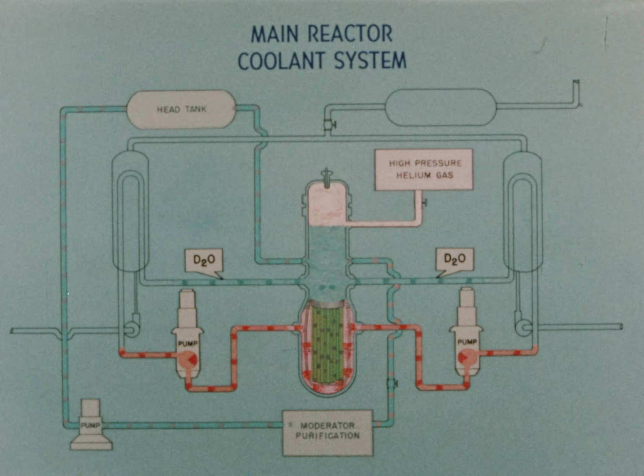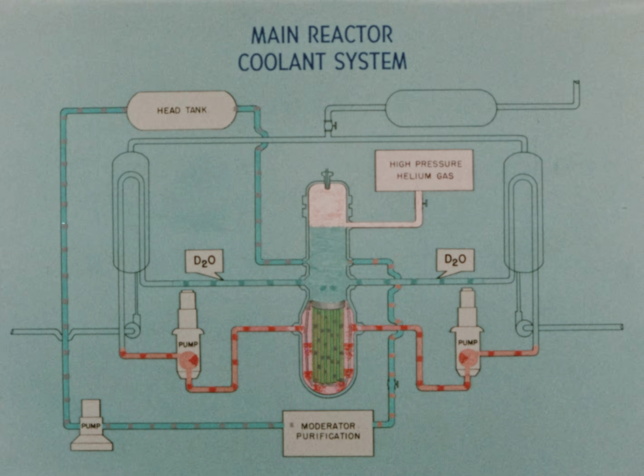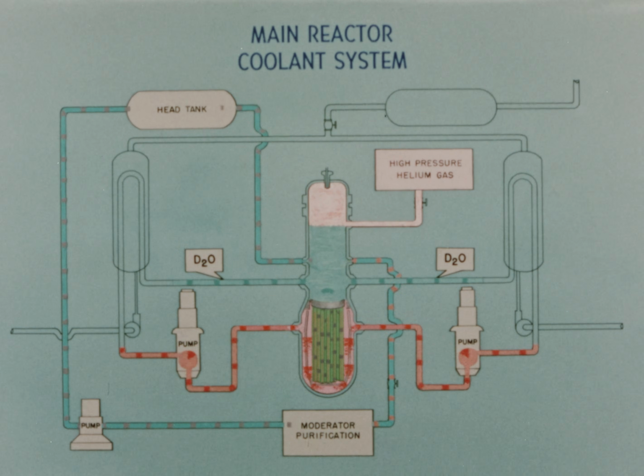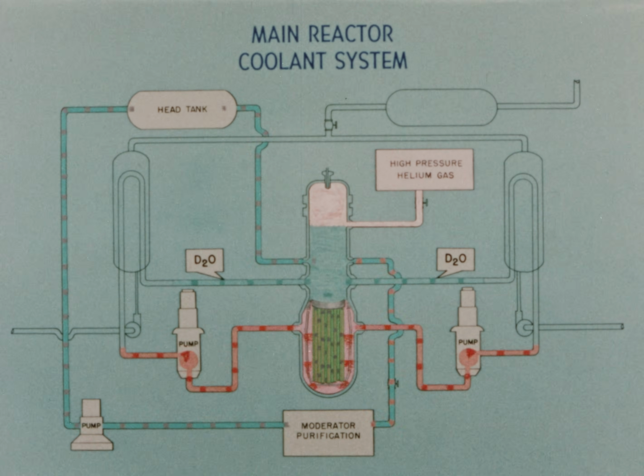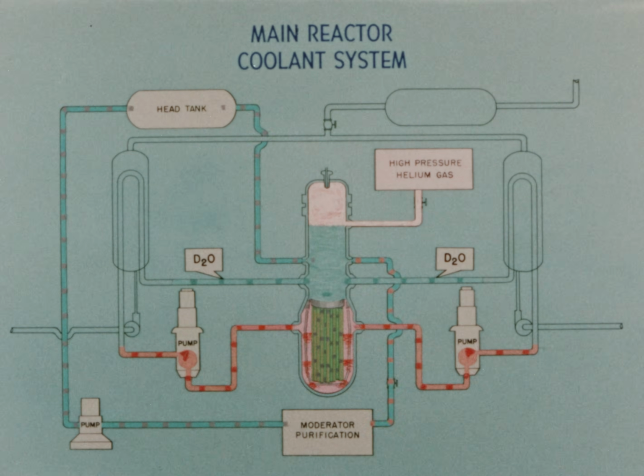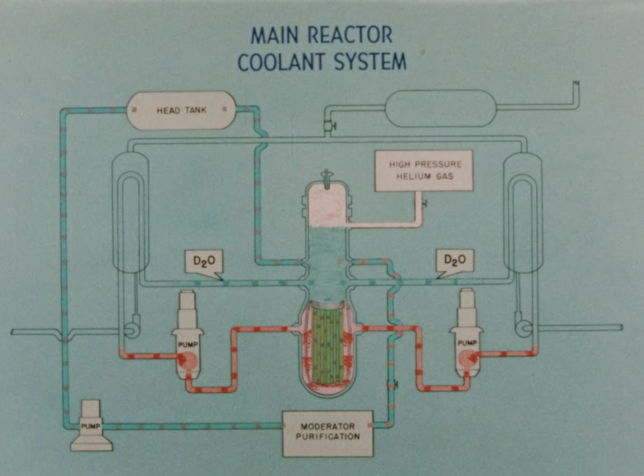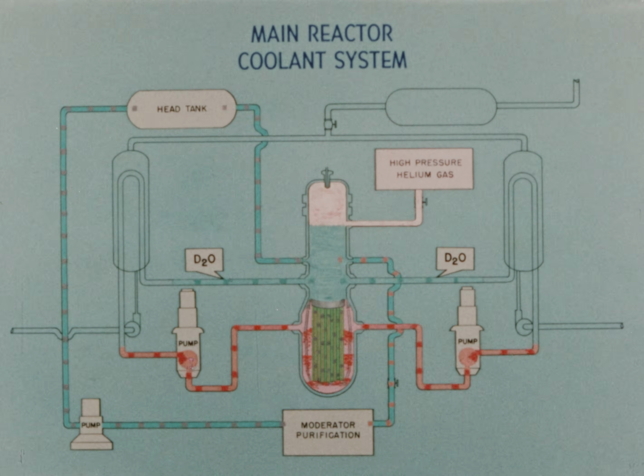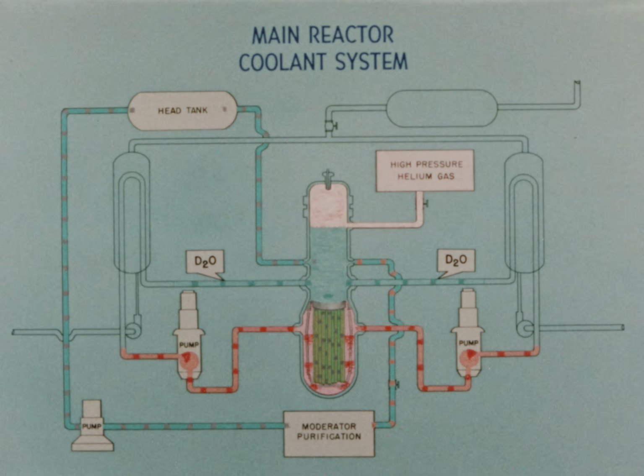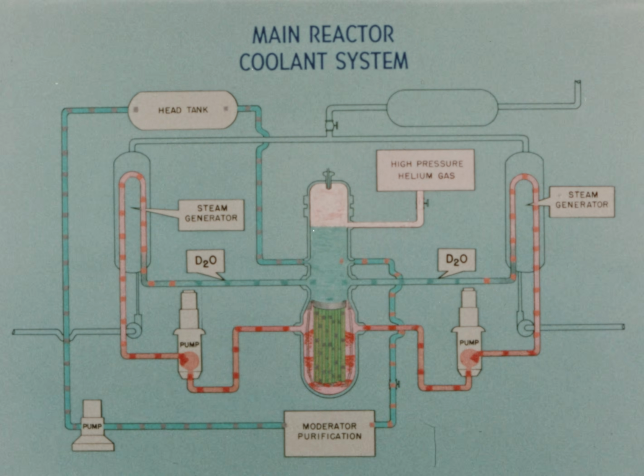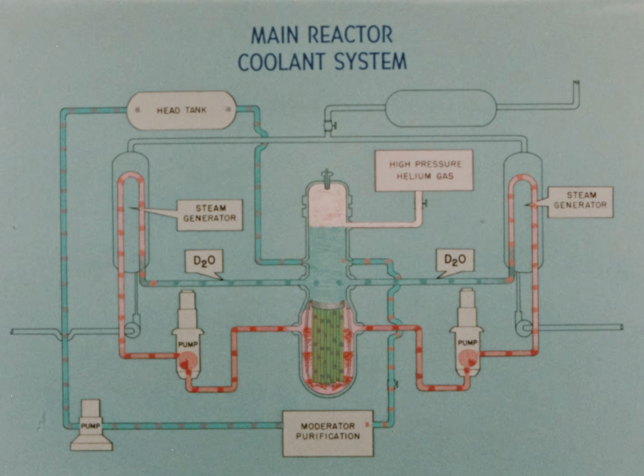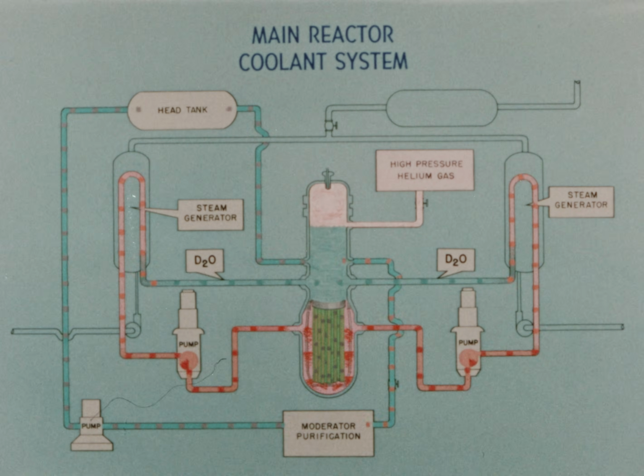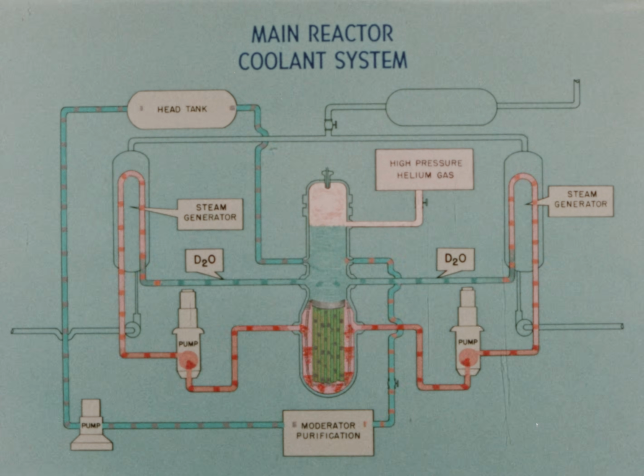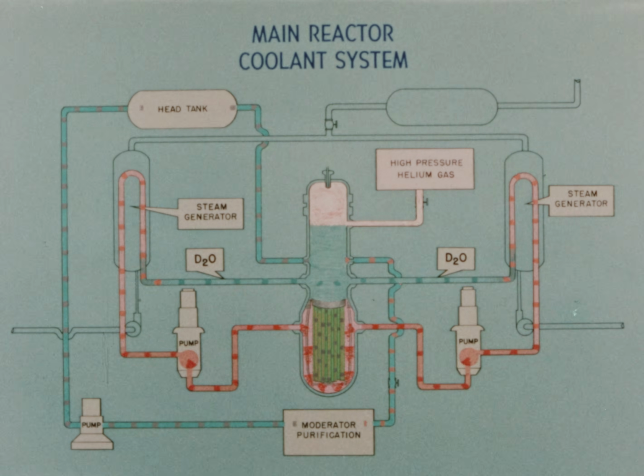A continuous purge of moderator from the reactor through filters and deionizers maintains the heavy water purity. A pH of greater than 10, required to protect the carbon steel piping and components from corrosion, is provided by addition of lithium hydroxide to the system. Heat generated in the reactor core is dissipated through two large steam generators, each extracting approximately 30 megawatts of reactor heat at rated conditions.